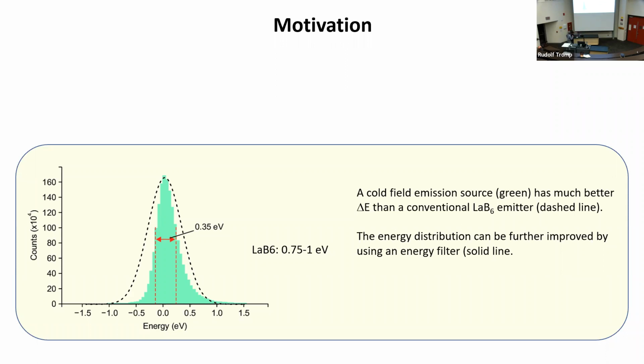So this is the energy distribution of a LaB6 emitter. It's a broad Gaussian, width of about 3/4 to 1 eV or so. The cold field emitter has a full width half max of about 0.25 to 0.35 EV. And we can just pick out this narrow band using the energy filter. So first we make the energy distribution Gaussian, right, symmetrical, and we can make it much narrower.